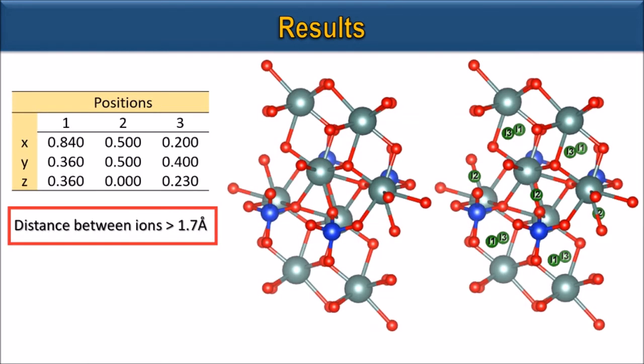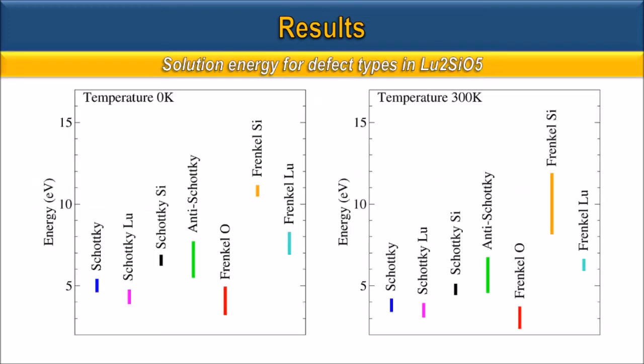The interstitial defect positions considered for both structures are shown in this table. The interstitial positions were chosen considering the empty volumes in the unit cell for both structures, and taking into account a minimum distance of 1.7 angstrom from the interstitial site to the first neighborhood species.